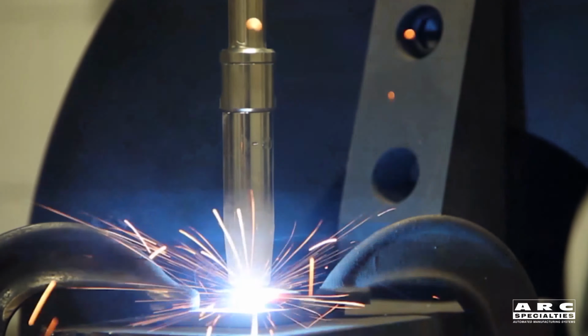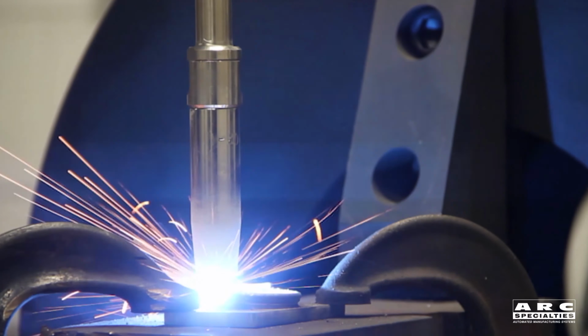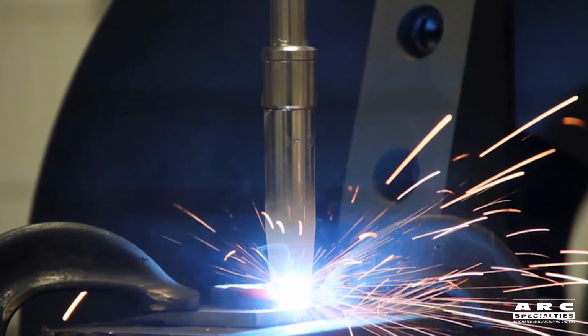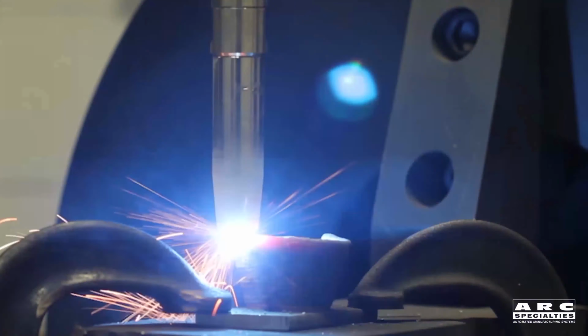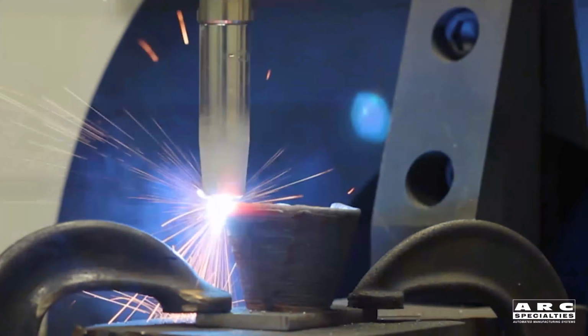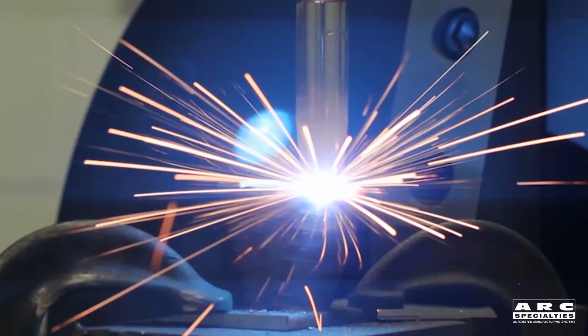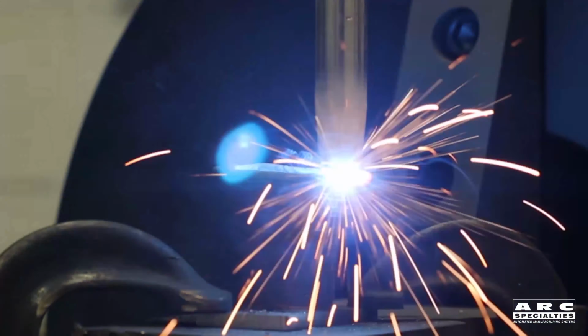What's the deposition rate on this one, Jim? 1.6 pounds per hour. So relatively low deposition rate. This is what we'll do for fine details. And how are you controlling the interpass temperature to maintain the mechanical properties? For this specific part, we just had a simple cool down time.